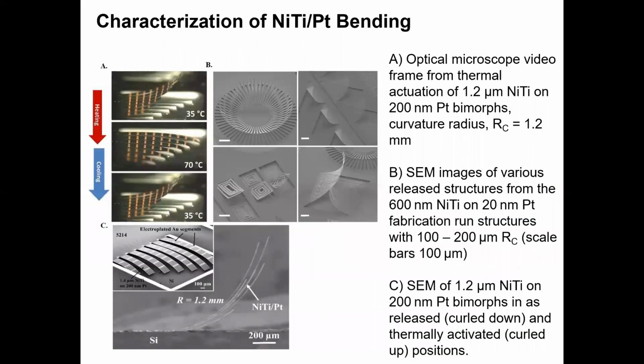So this slide overviews some of the characterizations done on this NiTi platinum bilayer actuator stack. Figure A is characteristic of the thermal actuation cycle for a typical NiTi platinum SMA-MEMS actuator. The cantilever array curls with some radius of curvature, and then when heated to 70 degrees, which was consistent with the stress versus temperature loops, the film undergoes a phase change, and therefore large nonlinear deflections upwards result from that. Upon cooling to room temperature, the actuation was shown to be fully reversible, which is characteristic of the two-way shape memory effect I had originally sought to achieve.